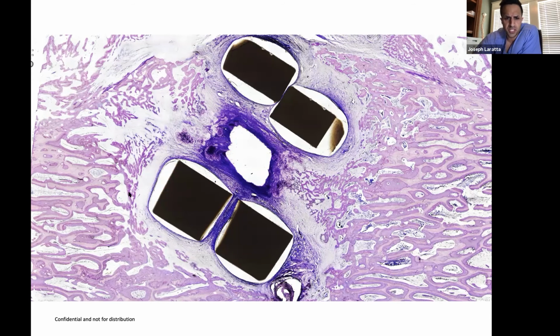This is a really nice picture because you can see that now you don't see really any bone formation around the PEEK itself. You actually see relative area of maybe apoptosis or fibrous formation. You see this kind of almost shielding of bone formation. And where the graft was placed at 8 weeks, you can see that there's osteolysis essentially of the iliac crest bone graft that was placed between the cage. And some other in vitro studies with PEEK have been shown that PEEK itself can induce mesenchymal stem cell apoptosis, and that may be part of what we're seeing here. Again, that's just speculation.